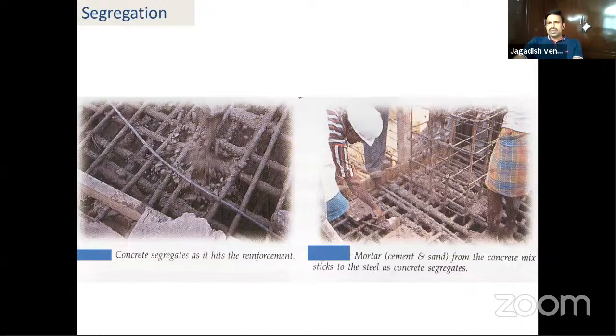But when you're placing the concrete in the reinforcement, usually we call it the free fall height of the concrete. As per IS, it should be 1.5 meters. Suppose you are placing normal concrete, what happens? The mortar gets stuck to the reinforcement, and the other particles like sand and particularly the coarse aggregate particles get separated out. Only the mortar gets stuck to the steel, particularly in congested reinforcement. So this is the common segregation we observe in many of the sites.